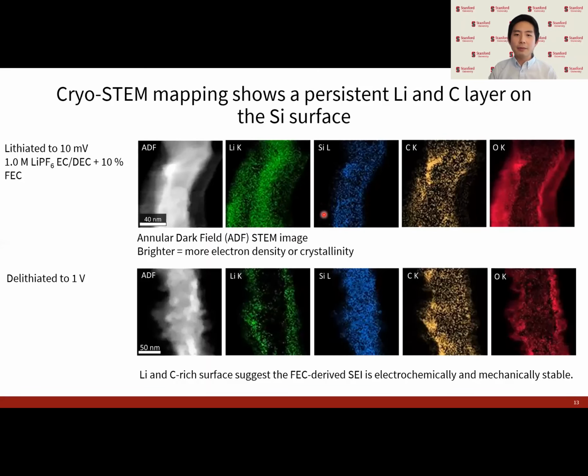And on delithiation, we can see large differences as well. The lithium remains enriched in the SEI layer along with the carbons, suggesting that this organic SEI, this poly-VC layer, is very stable on delithiation.